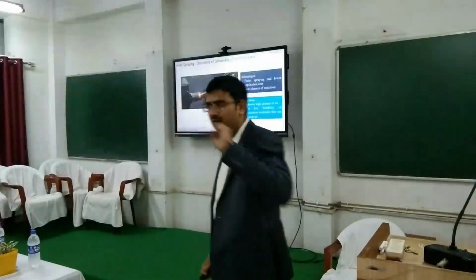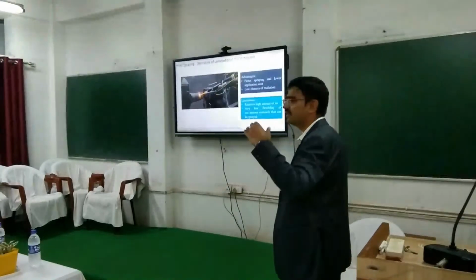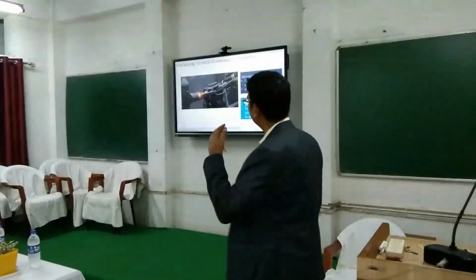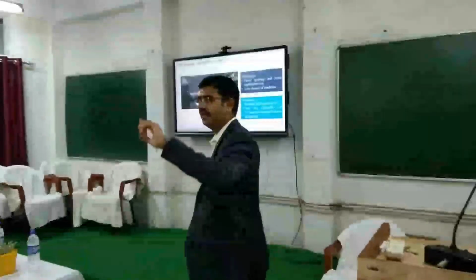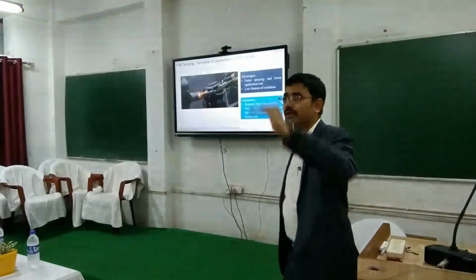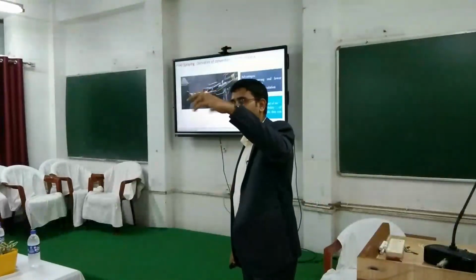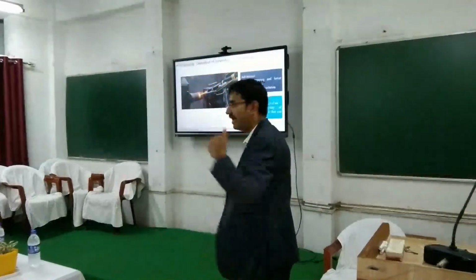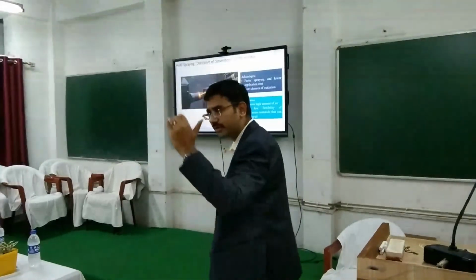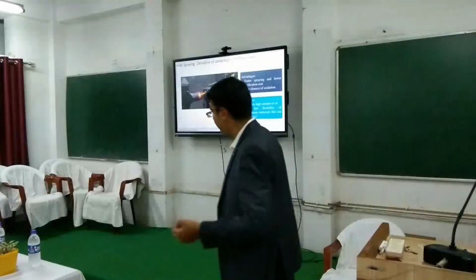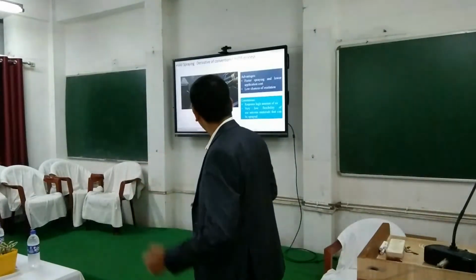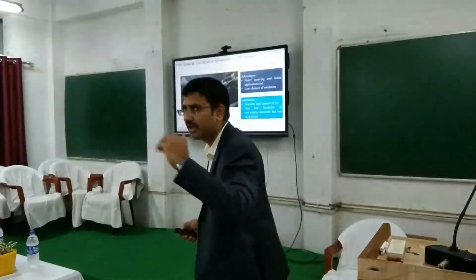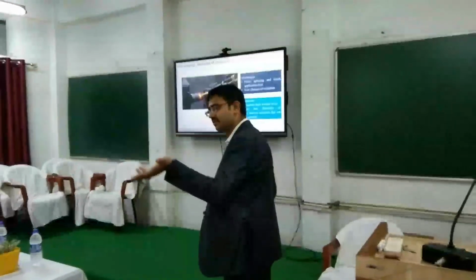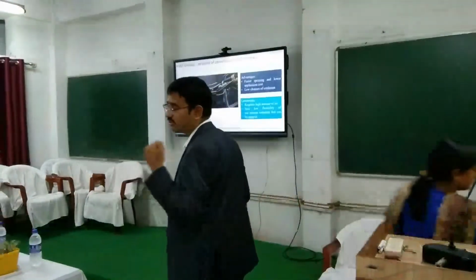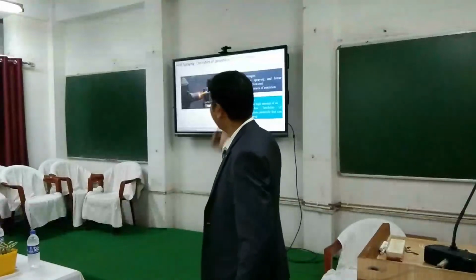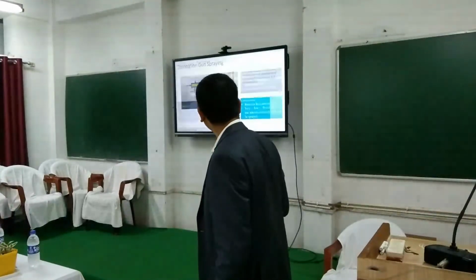Now the oxidation problem was troubling people, so they wanted to reduce the oxidation issue. So they started sending an air and fuel mixture. Earlier it was oxy and fuel, so the temperature of the particle getting melted in the combustion zone was higher. Now they started sending an air fuel mixture, so the temperature slightly came down because you have nitrogen also in air. As a result, the oxidation problem also came down. So some materials which are oxidation sensitive, which cannot be coated with HVOF, can be coated with this derivative of HVOF, which started to pick up.